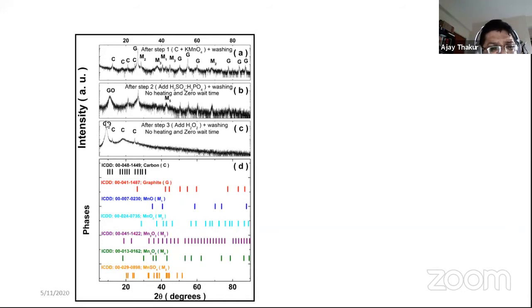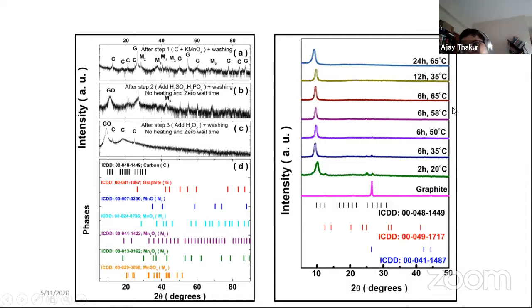So graphene oxide peak is typically about 10 degrees. So this is unique. What has been done is, as we plotted this, we could figure out what kind of secondary phases are persisting, and eventually with what kind of treatment most of these secondary phases are eliminated. And then we tried to play around with the other parameters, including temperature and time, and on a log scale reached a scenario where we could see that there are no secondary peaks.